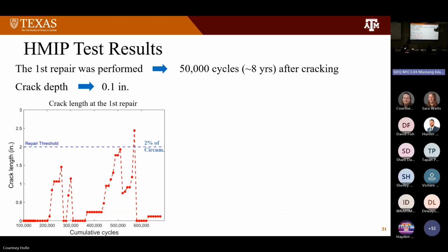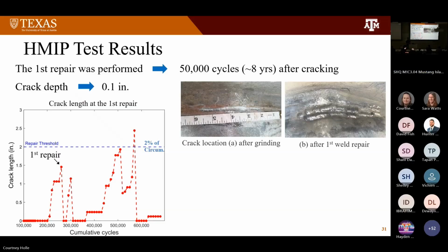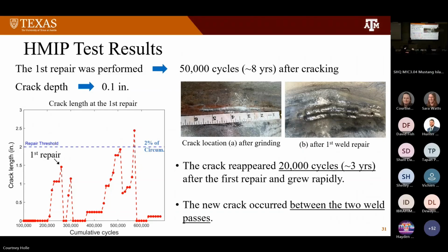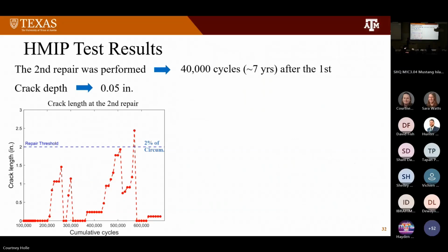The first repair was performed 50,000 cycles after cracking. The crack depth was measured at 0.1 inches here. Our repair involved grinding out the crack and applying 3 weld passes, 1 at the bottom and 2 cover passes above it. However, just 20,000 cycles after the first repair, the new crack reappeared between the 2 cover passes.